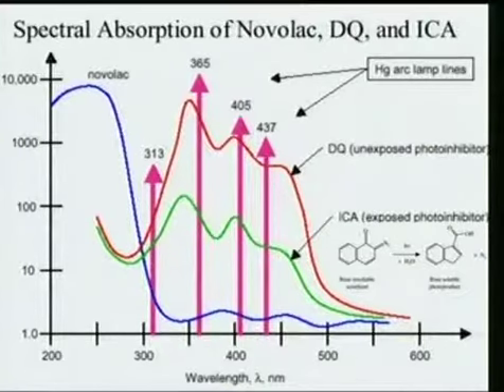All right, so we talked about the chemicals used for making materials sensitive at the different wavelengths. I like this plot because there's a lot of data in this plot. For example, I told you about the resist maker's holiday. That's here. Diazoquinone, we use the arc, the mercury lamp, as Andy was talking about, and then we went over to the lasers. This is indene carboxylic acid, undergoes this chemical change, right? We expose it to light in the presence of water. It gives off nitrogen and this base-soluble chemical, and that's why we use KOH or tetramethylammonium hydroxide as a developer. Likes dissolve likes. So when I expose it, this area of the photoresist is now sensitive to that base developer.